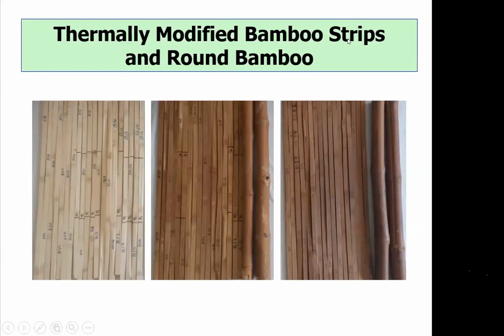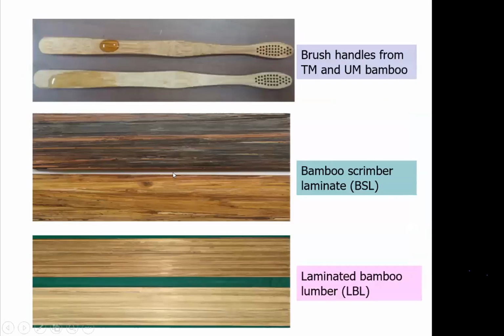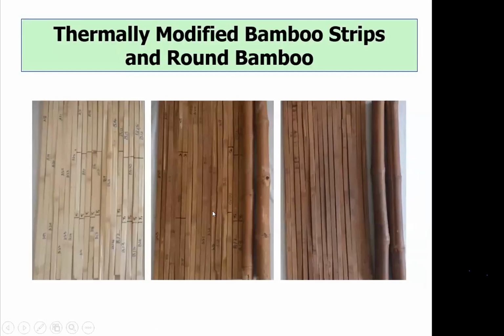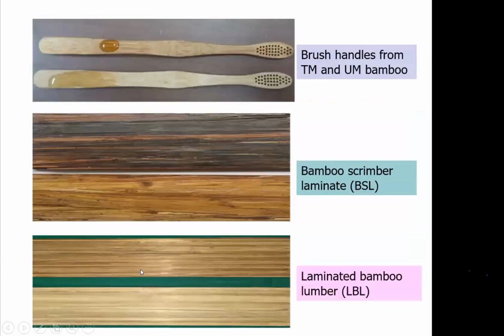This is thermally modified bamboo strips and round bamboo, you can see these are the strips. Here we have not given any kind of treatment to them, but this is mild treatment, and here is severe treatment given to the bamboo strips and round bamboo. And then these strips can be used for converting into laminated bamboo lumber. So here, this is the laminated bamboo lumber, this is control, and this is the thermally treated. And similarly, bamboo scrimber laminate, this is untreated, and this is the treated one.